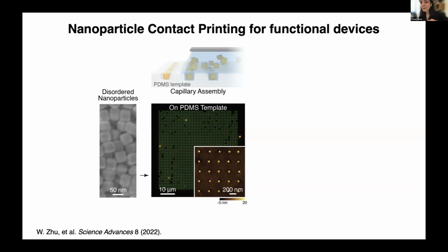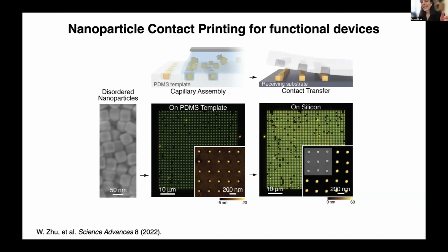And when it comes to nanoscale devices, surfaces and interfaces need to be accessible to be able to incorporate them into a device. So what we've done is add an additional step where we can now take the assembled particles and, without needing any sort of treatment to the surface, sacrificial layers, or high temperatures, transfer print them onto arbitrary surfaces with high yield. And we do that by engineering of van der Waals forces between the particle and the template, as well as the particles and the receiving substrate.